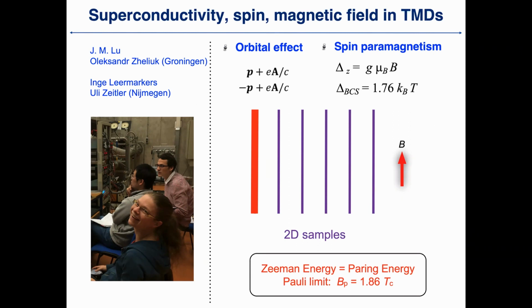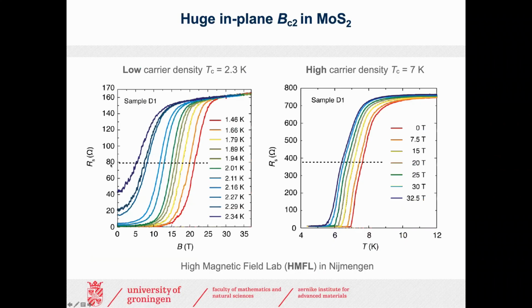So with this kind of motivation, we take the system and measure it at a high magnetic field, and we start to see something peculiar. Because if we induce a superconducting state with a very low TC, actually the upper critical field is very, very large. And here, with a TC of 2.3 K, the upper critical field is roughly like 20 Tesla. And by applying 20 Tesla, you can suppress the superconducting state. But if you induce a state with higher TC, even applying 32 Tesla, we are not able to. So 32 Tesla means that we can continuously apply the field there due to the heating effect. Then with this B field, we cannot even suppress the superconductivity completely.